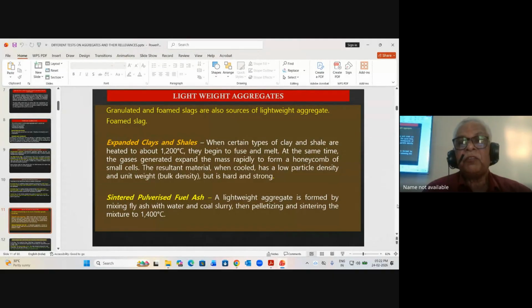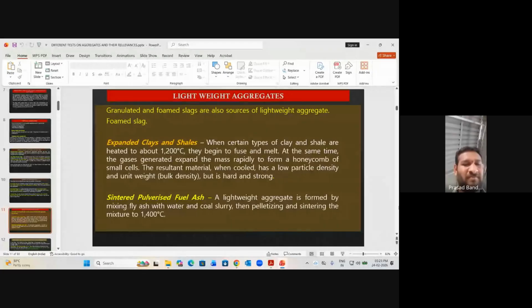There are lightweight aggregates like expanded clay and shales. They are manufactured from clay and shale heated to about 1200 degrees. When they begin to melt and fuse, some gases are generated, which expand and form honeycombs, forming small cells in the aggregates. Sintered fly ash is another typical one, made from fly ash with water and coal slurry, and sintering.